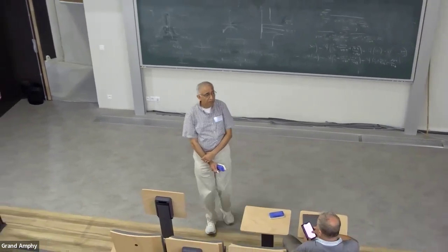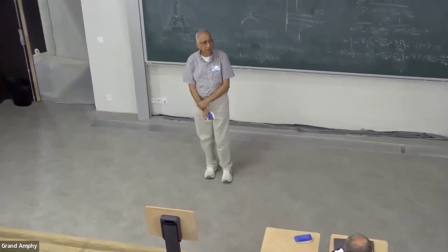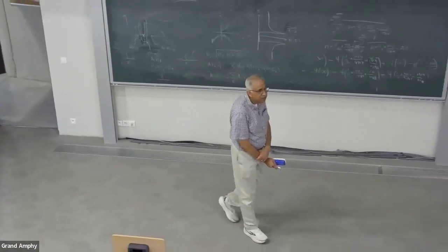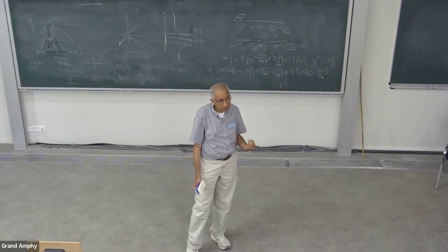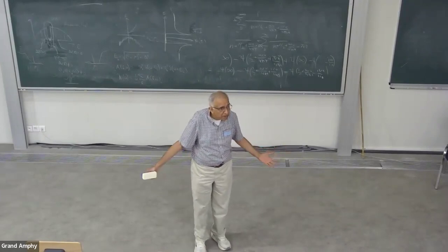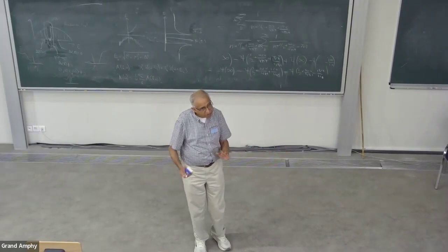In fact, from microwave absorption and thermal Hall, it's known that the mean free path for nodal quasi-particles in YBCO at very low temperatures is a micron. So something dramatic happens when you cool through Tc.